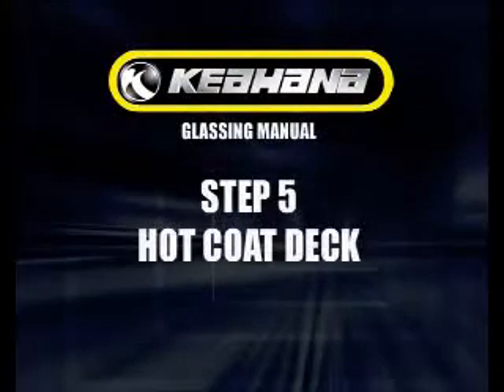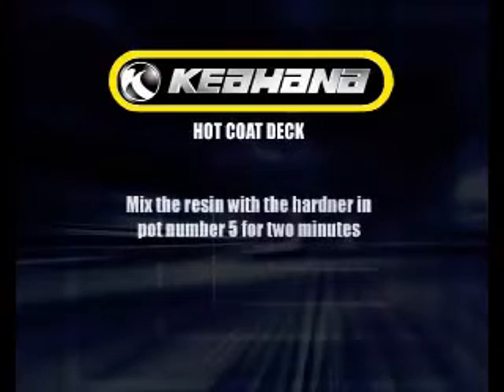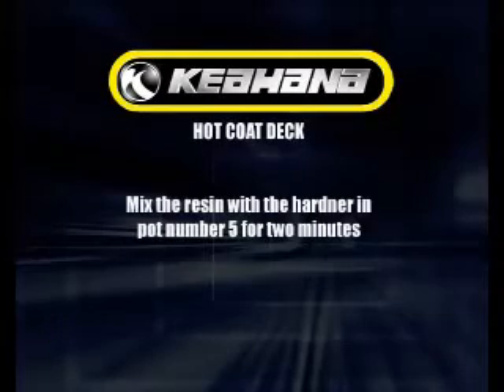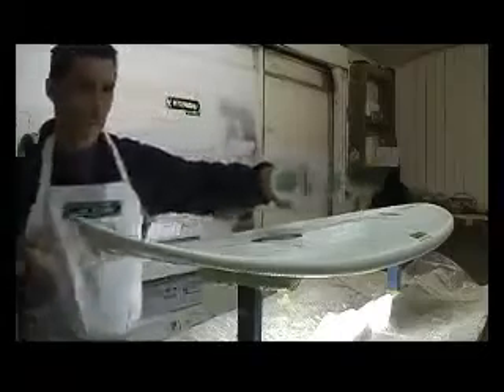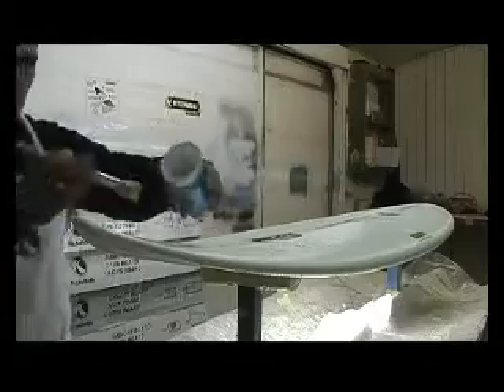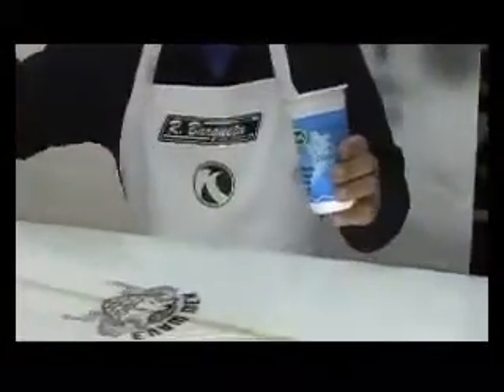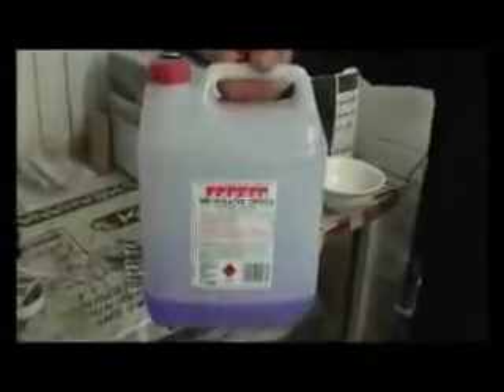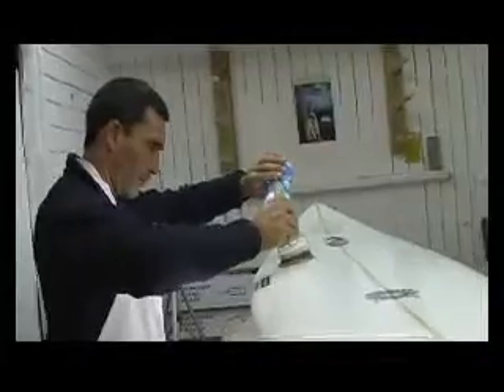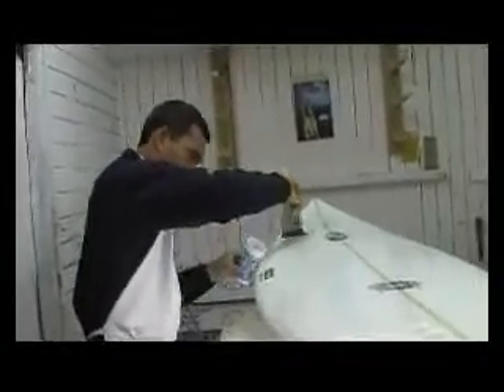Hot coat deck. Mix the resin from the sachet with the hardener in pot number 5, hot coat deck. Mix it for 2 minutes, ensuring the entire pot is well mixed. Using a clean brush, spread the resin over the deck, leaving it flat and uniform. After every use, the brush must be cleaned with methylated spirits to remove any potential contaminants. The brush must be completely dry before being used.